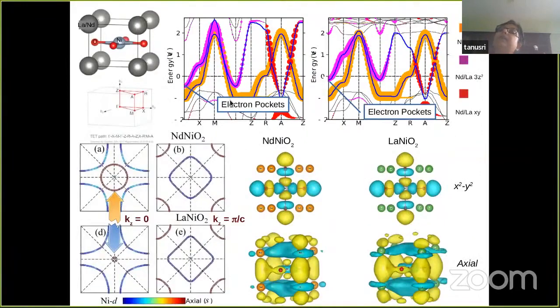So this is the density functional theory band structure of the compound. We took two compounds, namely the lanthanum nickelate and the neodymium nickelate. On the left is shown the band structure of the neodymium nickelate, and on the right is that of the lanthanum nickelate. And what is interesting, you of course have this single band that is crossing the Fermi level, which is basically the nickel x² minus y² band shown with this orange fatness.